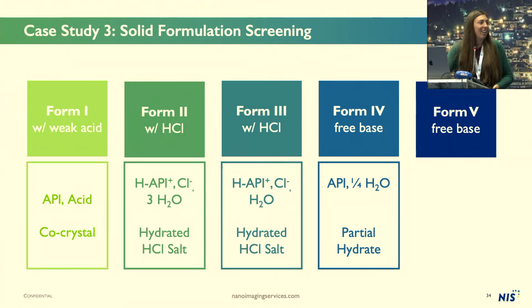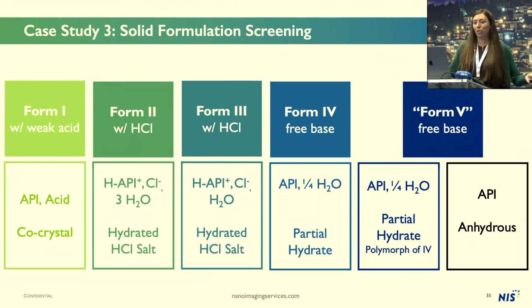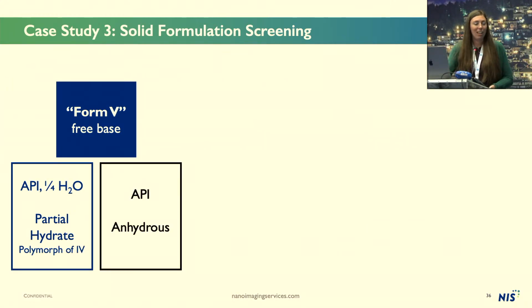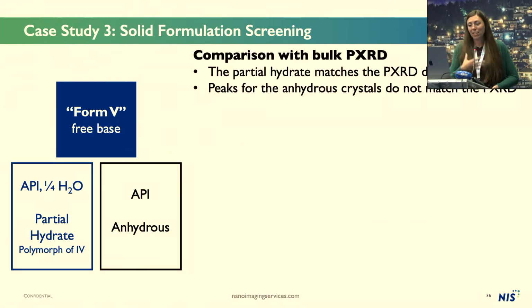Onto form 5. So form 5 was a bit interesting as well, in that we actually solved 2 structures from their one sample. So we were able to determine another partial hydrate. This is a different polymorph of form 4. And then we also solved the structure of an anhydrous form. So this is a bit puzzling, what's going on here. And we went and looked at a comparison with the bulk powder diffraction. And we found that the partial hydrate structure matches quite well with their powder diffraction, but the anhydrous crystal doesn't really match the powder diffraction. We didn't really see the peaks lining up there.